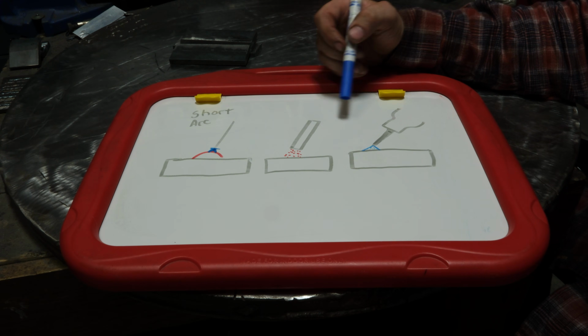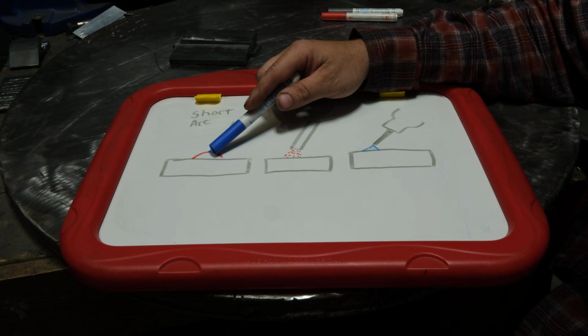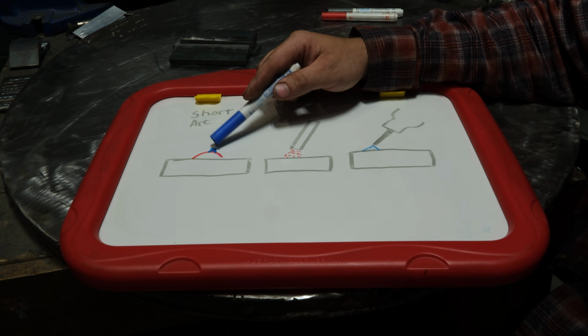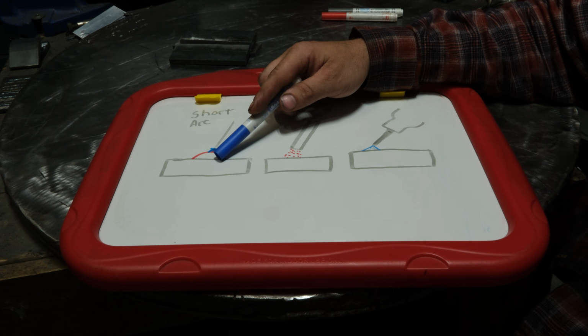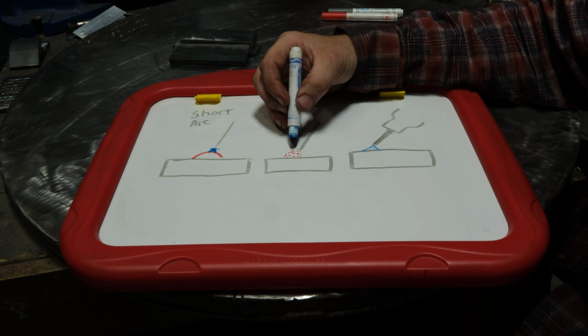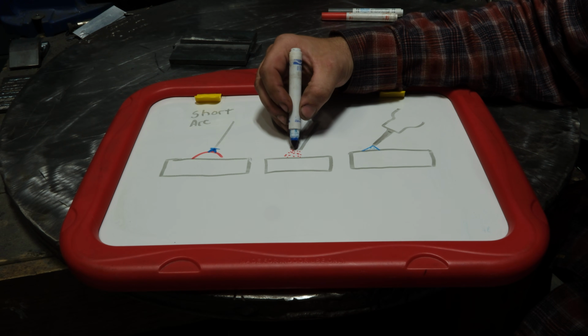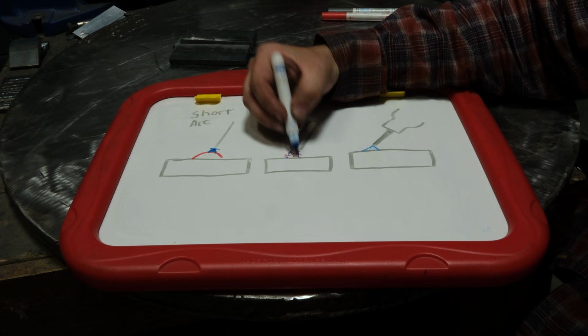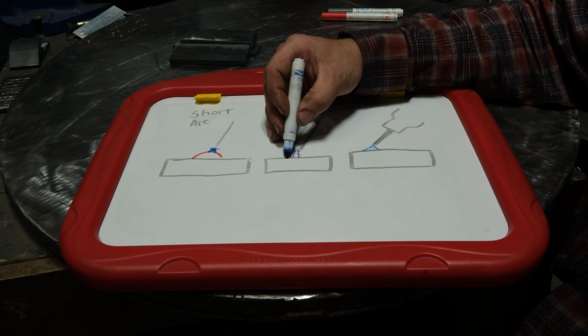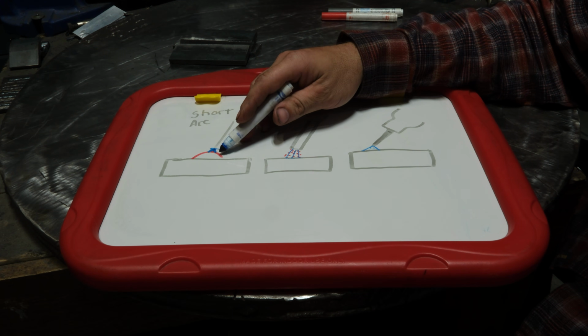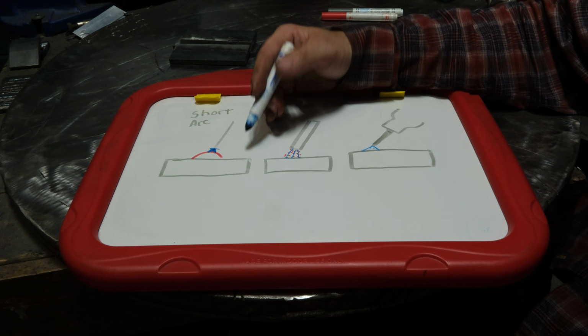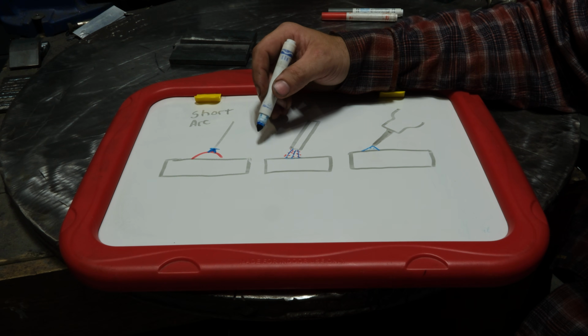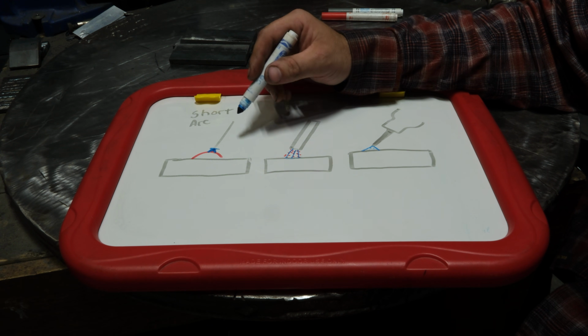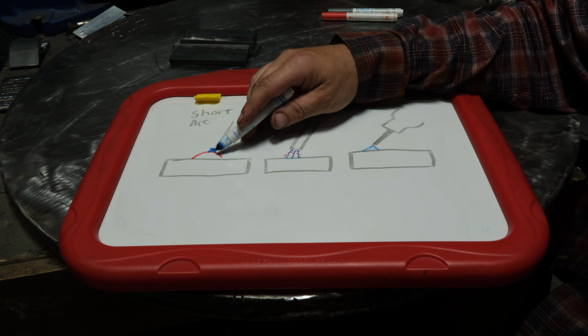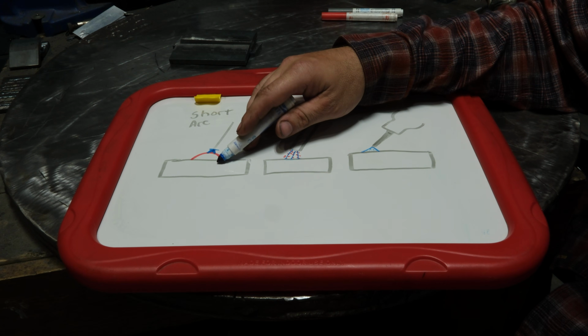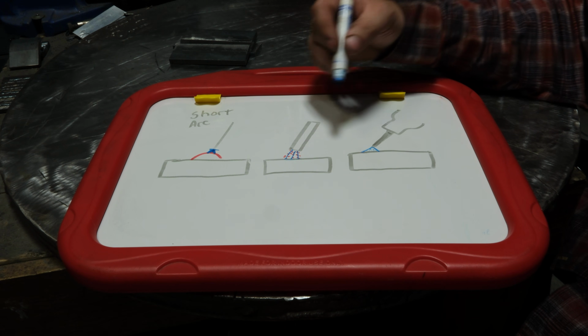Depicted here is stick welding and TIG welding. You'll have to mind my poor drawings. So as we established, your arc exists more or less in the middle of the puddle, or the top of your molten puddle to the wire, and the heat input is pretty far away from the actual base material. With stick welding, it functions more like a globular transfer, like we talked about with 100% CO2. You have bigger hunks or balls of metal, and then you have an actual arc present in those balls of metal. Therefore, that arc has a much easier time actually hitting your base material instead of trying to get through and melt through molten metal. And that's, again, going back to the short circuit process. The higher your wire feed speed, the higher the risk you have of producing a tall bead, especially if your voltage isn't up high enough. And then you have that much more material to attempt to get your heat to go through in order to hit the base material. Well, with stick, you just don't have that issue because, again, it's similar to globular.